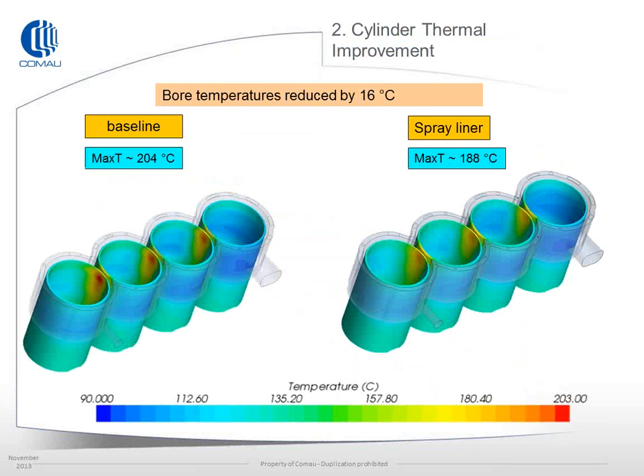As you go into looking at modeling that, what you can see is that on a baseline study, we were able to see that liner temperature dropped 16 degrees Celsius. A significant improvement. The biggest improvement was dropping the max temperature to below 190, particularly in the bore bridge area. Definitely a significant source of knock for most engines.